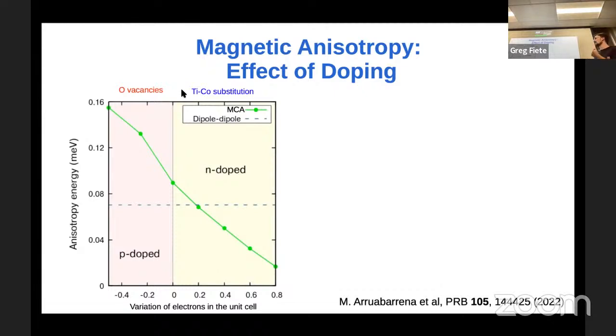And we also consider the opposite case, the N-doping, which would be having anti-site disorder, or having some cobalt places filled by extra titanium, instead of cobalt having titanium. This has also been seen in older experiments of these kinds of compounds. It's also reasonable to happen. What we did is compute the anisotropy energy with respect to the variation of electrons in the unit cell that would correspond to these two different kinds of doping.